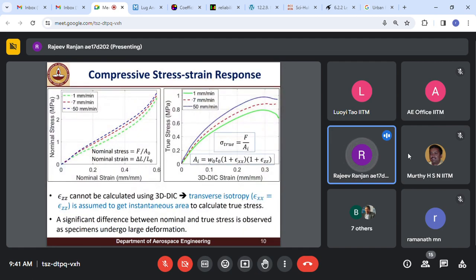This is a compressive stress strain response. Here, the first plot shows the nominal stress versus nominal strain plot, and this is true stress versus 3D DIC strain plot. There was a large difference in the nominal versus true stress responses. And similar to the uniaxial tensile loading, here also it was observed that the response was dependent on the displacement rate, and it was nonlinear.